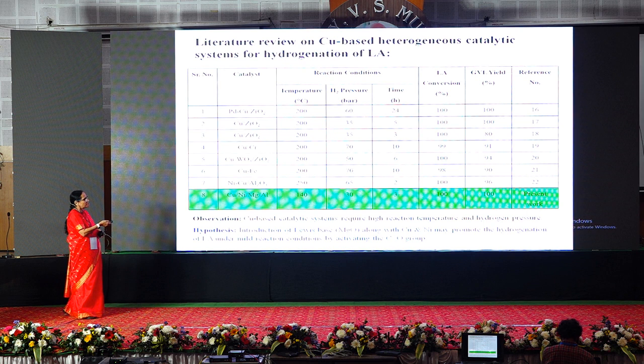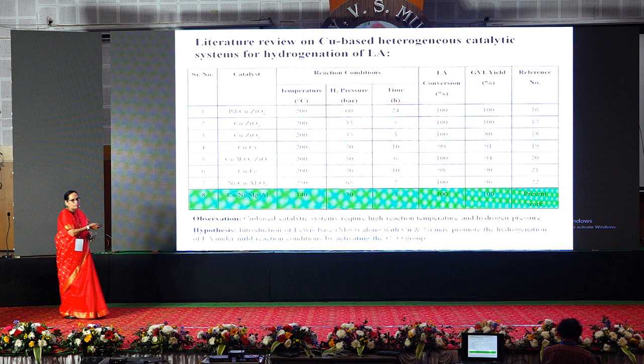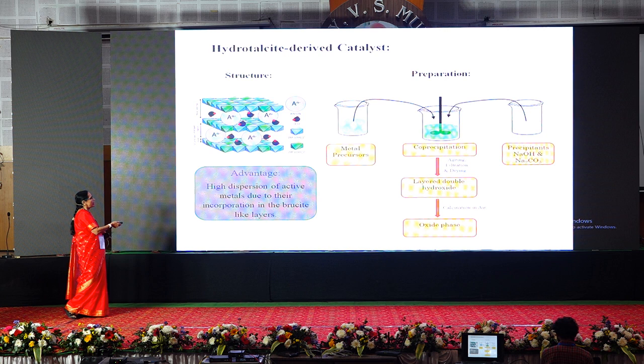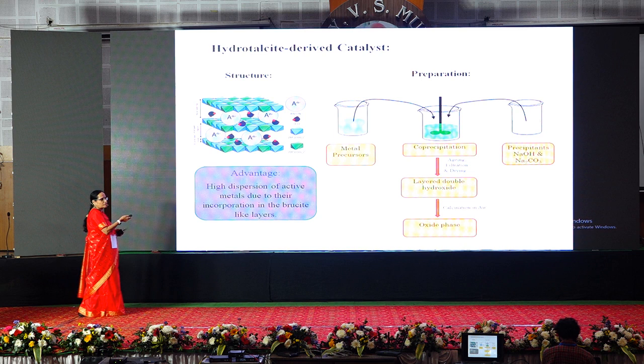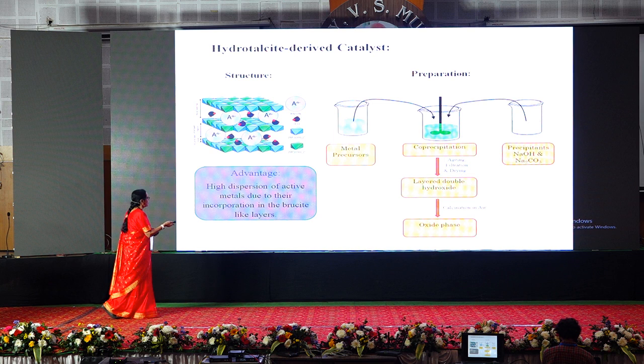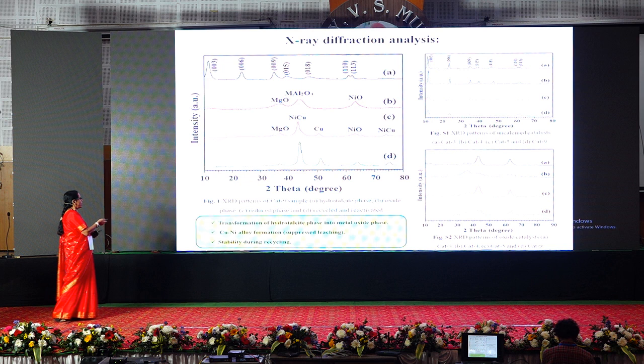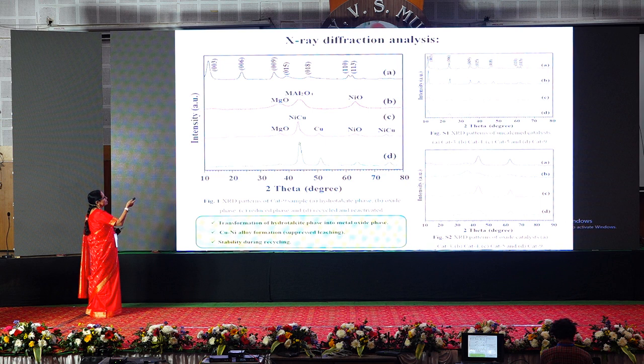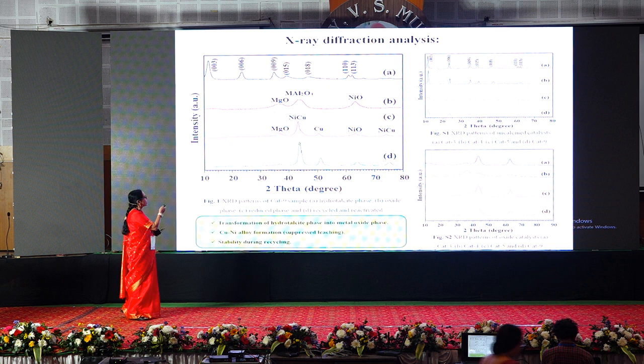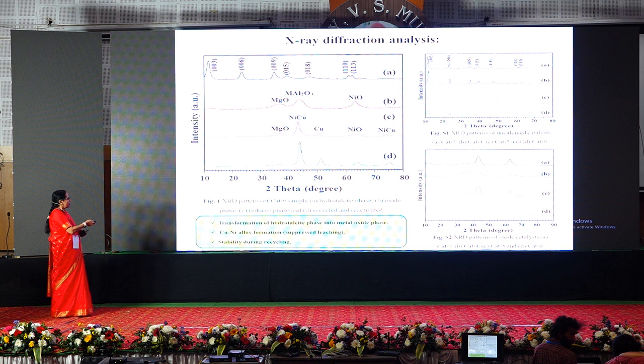And you can see the introduction of a Lewis base, MgO, along with the copper nickel may promote the hydrogenation under mild conditions. And it is easy to prepare, I already told you: take the metal precursors and coprecipitation, you make the pH 9, layered double hydroxide, calcination and oxide phase. And we have completely characterized this catalyst. First you see the magnesium aluminate, magnesium oxide and nickel oxide, and when you reduce it, you will get the nickel copper alloy, which is very good. The copper nickel alloy formation suppresses leaching and gives stability during recycling.